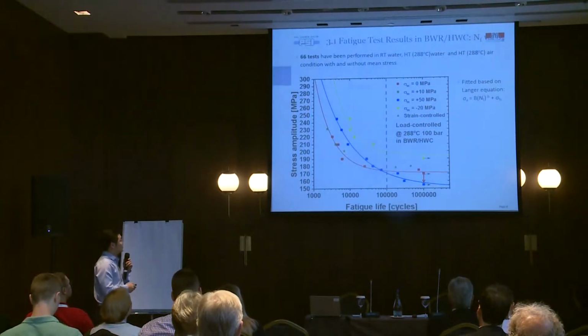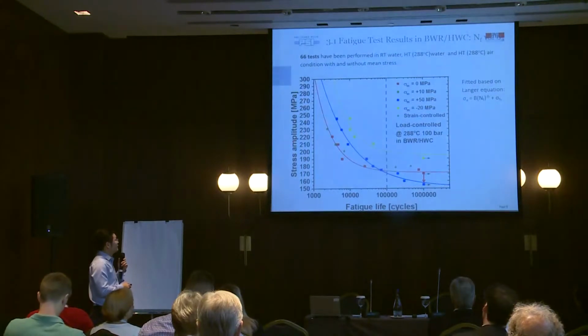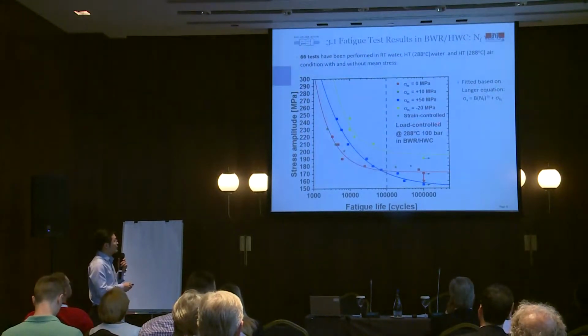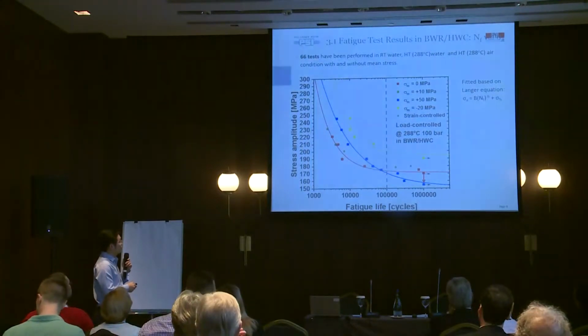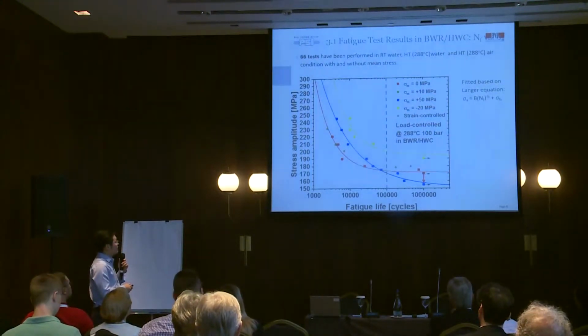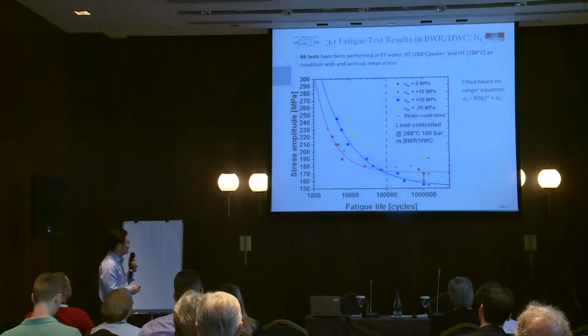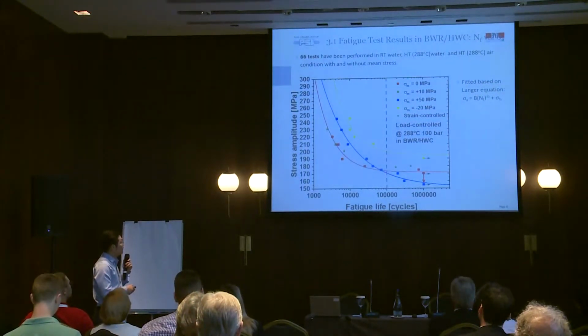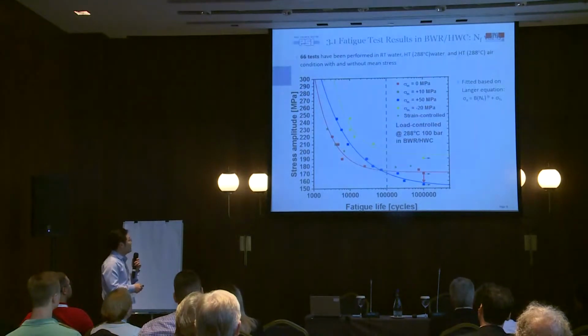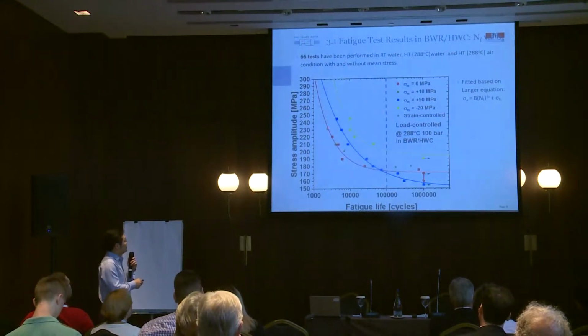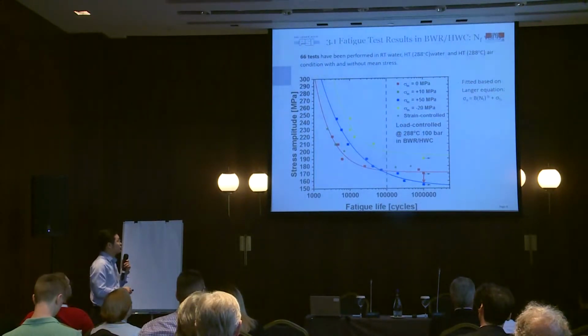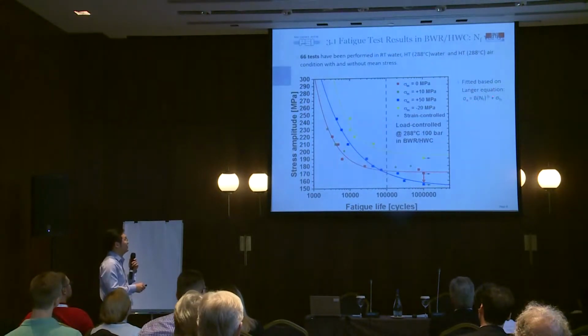If we divide this diagram into two halves, the left is low cycle fatigue, the right is high cycle fatigue. In the left region, we found that both positive and negative mean stress have increased the fatigue life. On the right, in high cycle fatigue, we found that positive mean stress has decreased the fatigue life and also the fatigue limit. On the other hand, minus 20 MPa has increased the fatigue life and fatigue limit. We also found the strain control test results correlate well with the load control test results, and the curve is fitted based on the Langer equation.